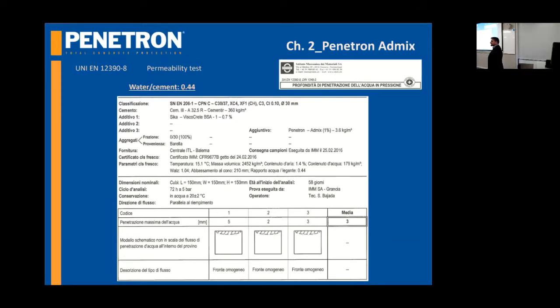Oh, it's a standard test. The standard one, with water penetration under pressure, it's EN 12390-8 or something. The machine is standard, so you apply five bars for 72 hours, then you cut the specimen and measure the water penetration. Five bars, I'm sure, and 72 hours, yeah, the standard conditions.